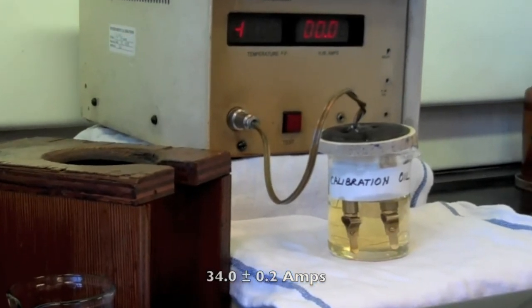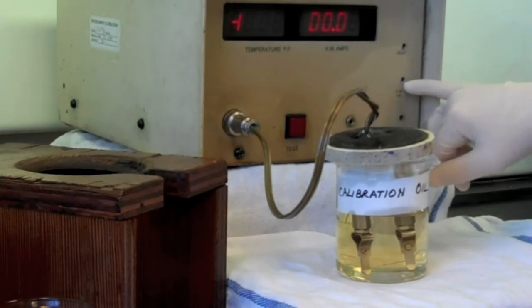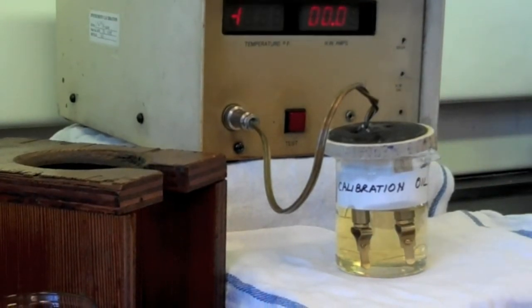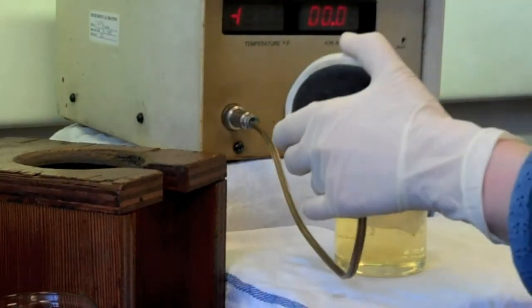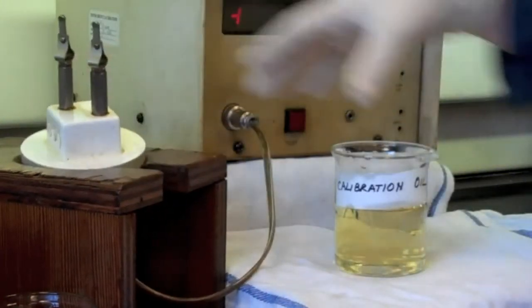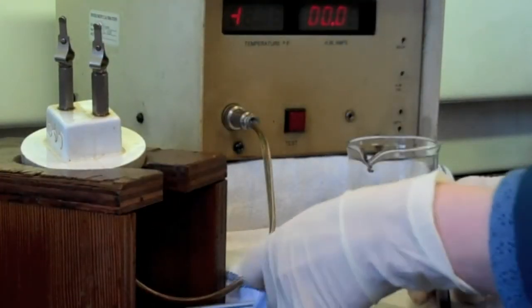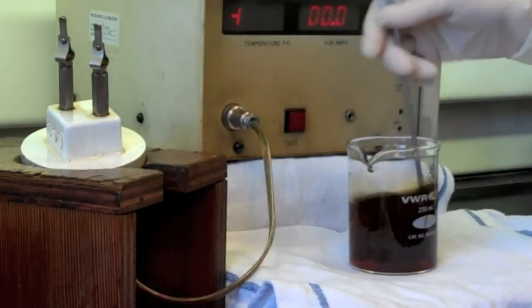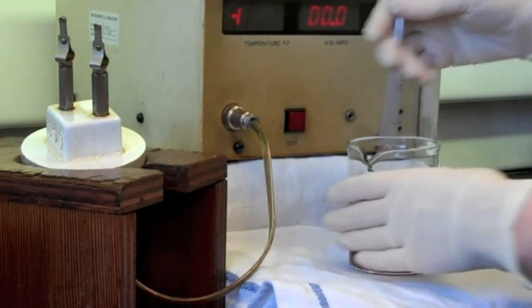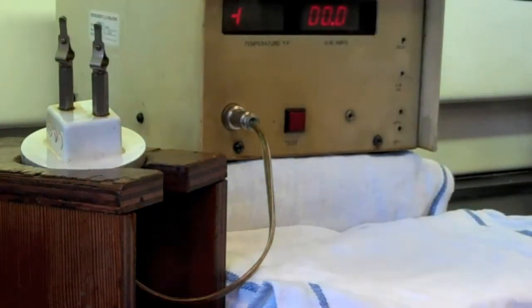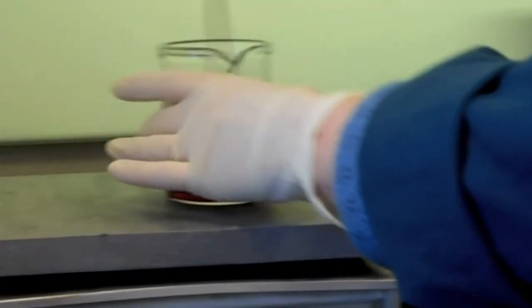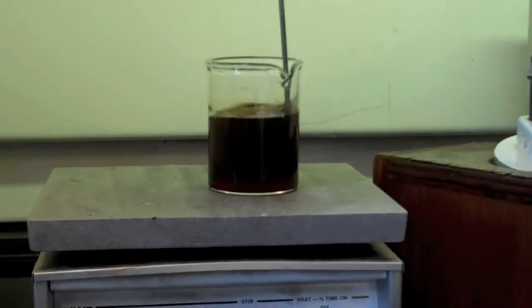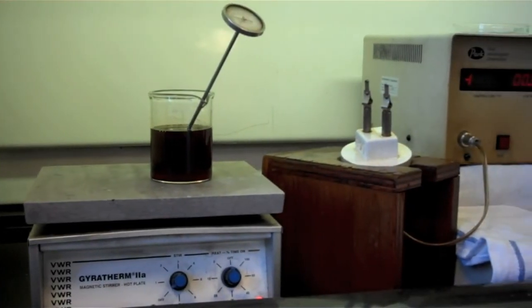If that's not the case, the apparatus has a calibration knob here that can be adjusted, and the test is repeated again until the value falls within the spec. Now that the apparatus is calibrated, we are going to take our oil sample, which is unused AAA oil, and repeat the procedure. Take 3 readings of the hot wire and do the average. First, we are going to heat it up to 140 degrees Fahrenheit, and then we are going to run the test.